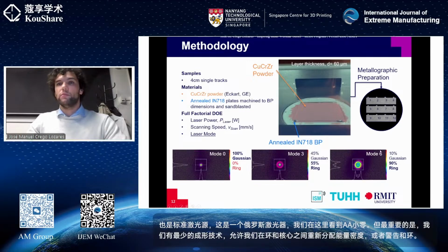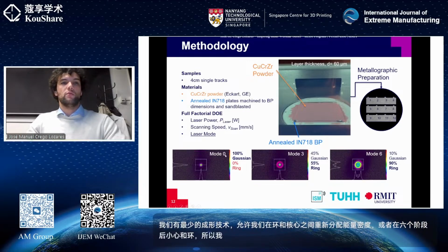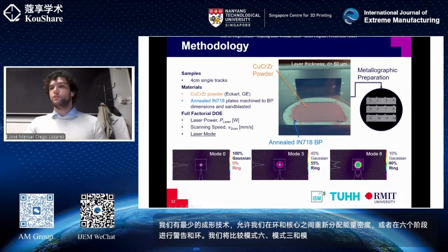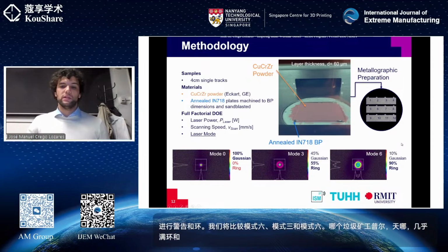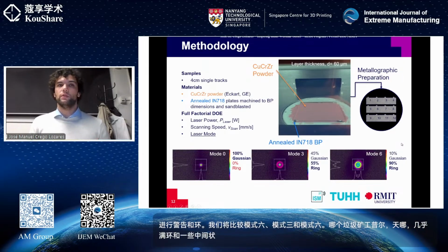So we will compare mode 6, mode 3, and mode 0, which we determine as full Gaussian, almost full ring, and some intermediate state. And we will see how they can deal with the retention of copper, as well as the possible defects that we can encounter.